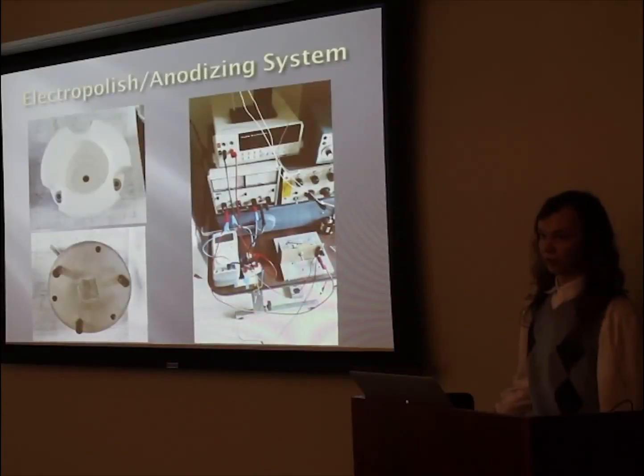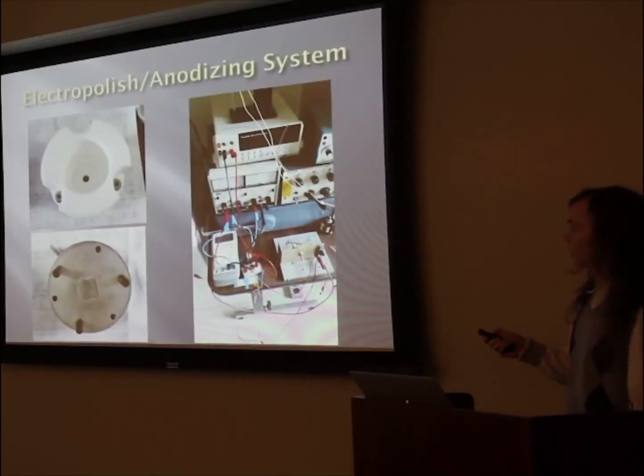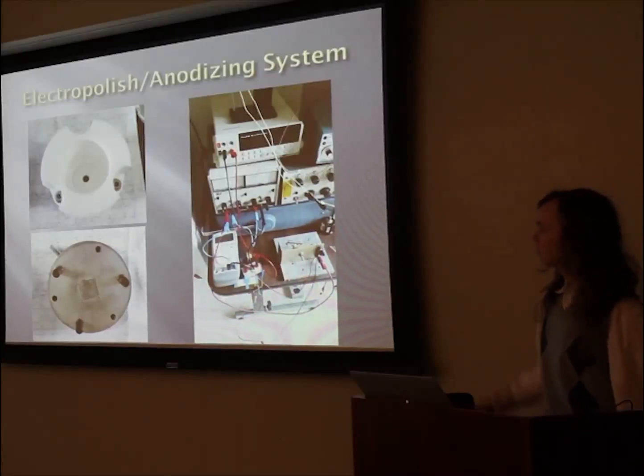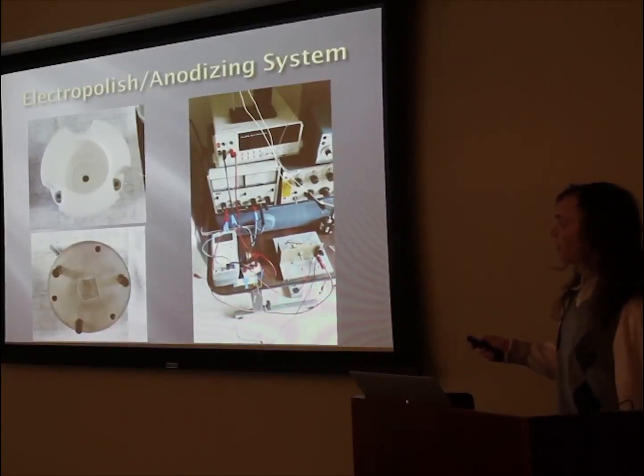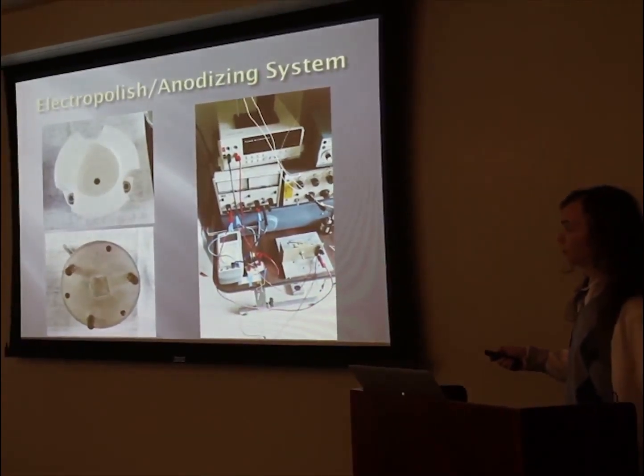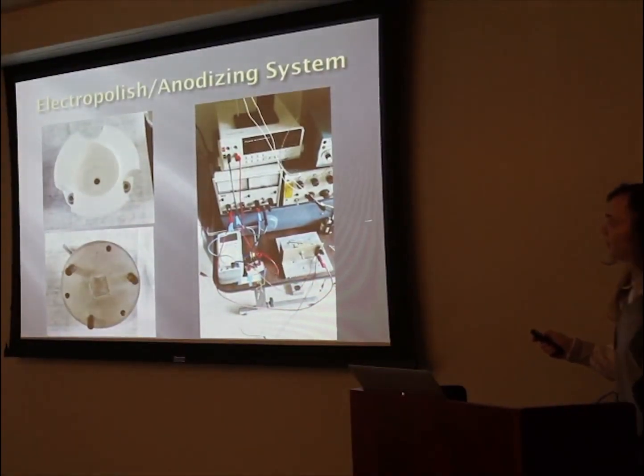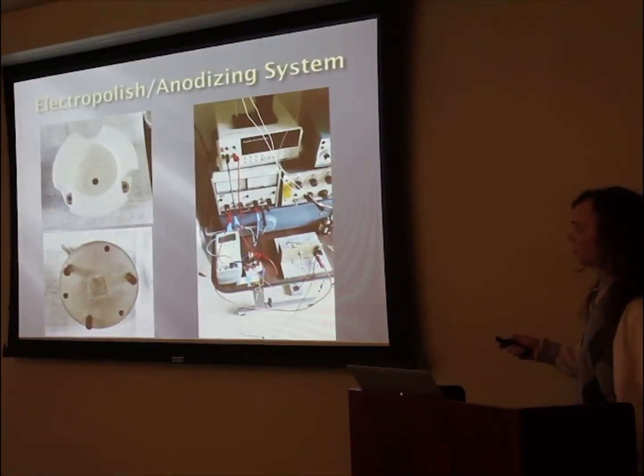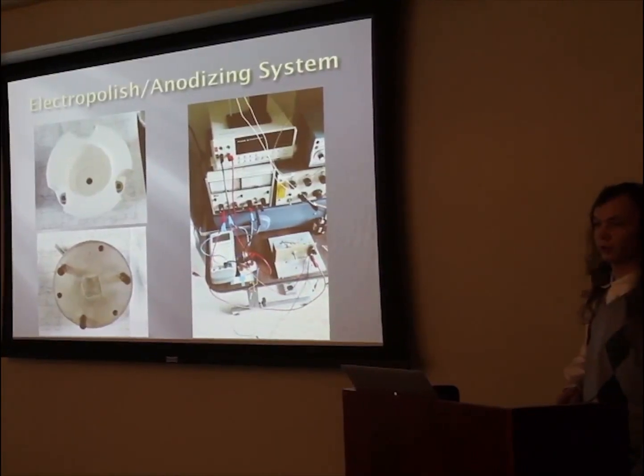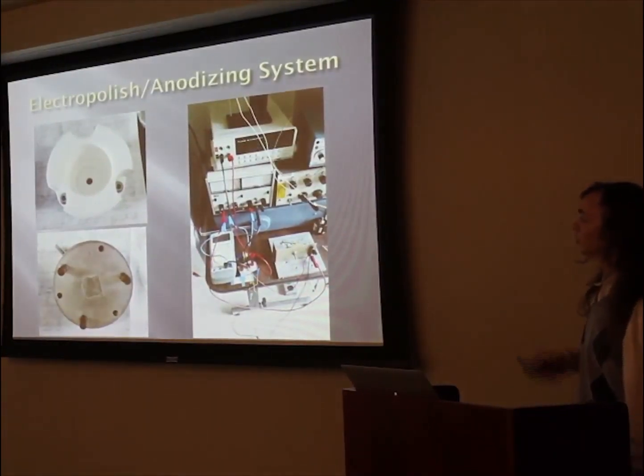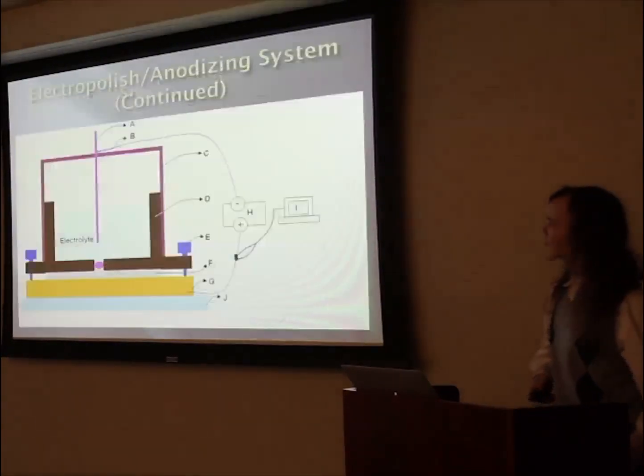So what does the system look like? So up at the top left over here, we have the top layer of our cell where you can put oxalic acid or electropolishing solution for either electropolishing or anodizing. And the bottom over here is a metal portion where in this tiny square here you can put your sample. So you combine these two together, you can fill it with acid or electropolished solution, and it allows you to push a current through it using this circuit setup we have here. So we can measure what is the voltage we're putting through the circuit, we can measure what the current is going through it, and other things like that.